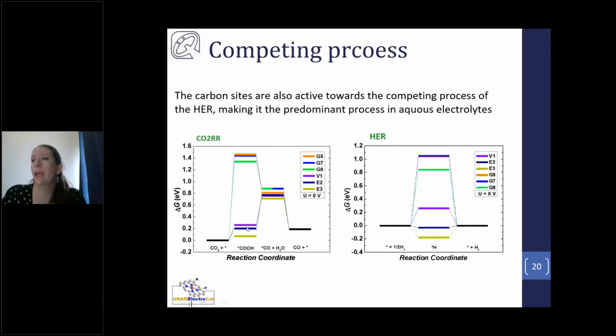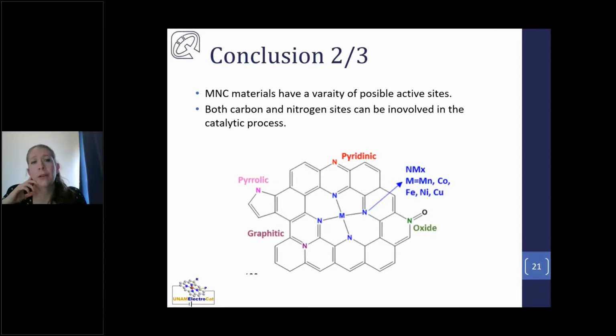And if, for example, we take this vacancy 1, that is the lowest overpotential for CO2 reduction, it also has a lower overpotential for hydrogen evolution reaction. So we never fully realized that carbon electrodes could reduce CO2 because the dominant process was hydrogen evolution reaction. But we should keep in mind that these carbon sites are not completely innocent as we would like them to be. So they are contributing to the reduction current. Maybe if we're working in aqueous electrolyte, they are only contributing with the competing process, but certainly in other electrolytes, they could even be contributing further in the reduction of CO2 to CO.